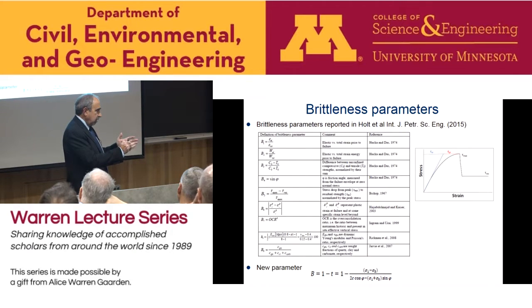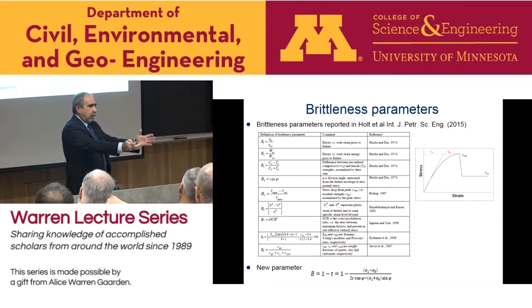We talk about brittleness, okay, and ductility. So most of these parameters actually were based on stress-strain curve, which is the ratio of the elastic strain over the total strain, or the elastic energy over the total, compressive strength minus tensile strength, different proposal, the friction angle. And in this definition, which people in the oil industry like because it's based on dynamic measurements. In the field, actually, they do dynamic measurement, wave propagation, seismic wave propagation, or sonic wave propagations. So if we know the dynamic modulus, then you can do correlations to get a brittleness number.